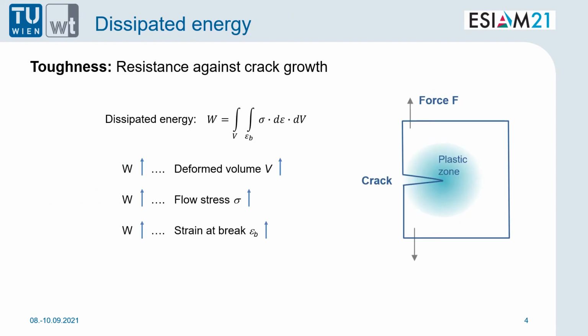From a material science point of view, this might give us new possibilities in designing materials and material combinations. One of the most serious issues in 3D printing materials, especially in systems using photopolymers, is the limited toughness and the unfavorable creep behavior of commonly available resins. In order to increase the plastic zone, which is here, around the tip of a propagating crack, and therefore increase the resistance against its growth, which is commonly used as a definition of toughness, the dissipated energy in the material has to be maximized. And this can be done by either increasing the deformed volume or the flow stress or increasing the strain at break.